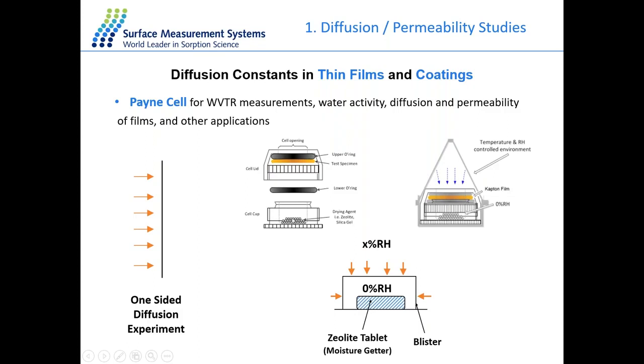We can also put some drying agent, which is shown here, in the cup here, like zeolite, silica, or molecular sieve, to avoid moisture building up in the cell and keep 0% relative humidity all the time throughout the experiment. Then we can change the outside concentration with the DVS system to different levels, and the vapor molecules will just go through the film from the top to the bottom in one direction only. And in that case, we can calculate the one-way diffusion coefficient or the permeability parameter for this thin film sample.